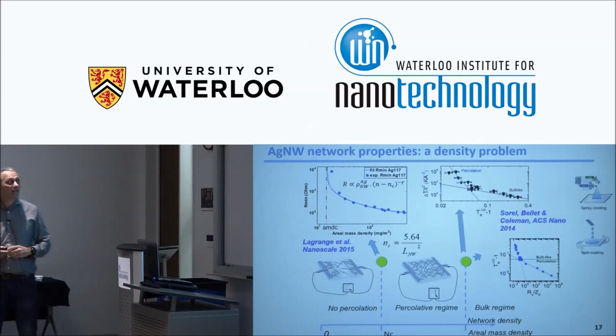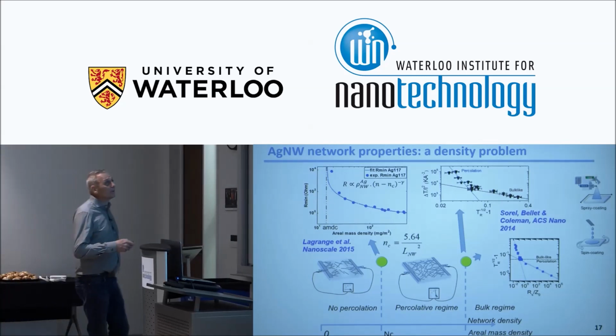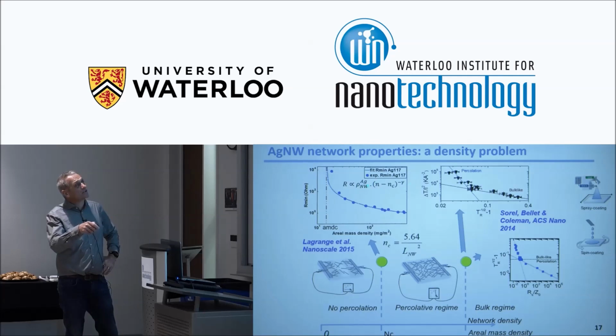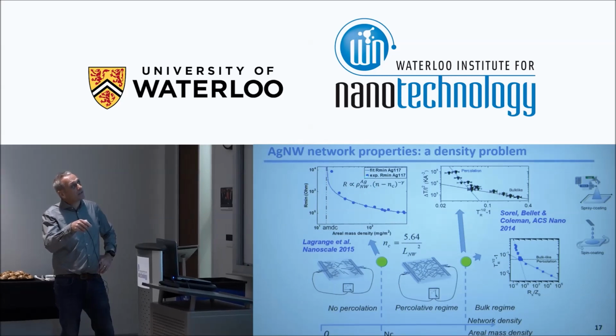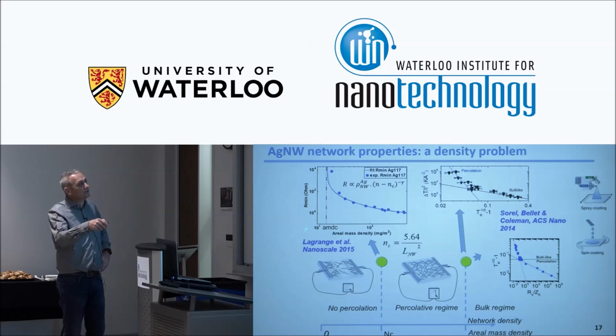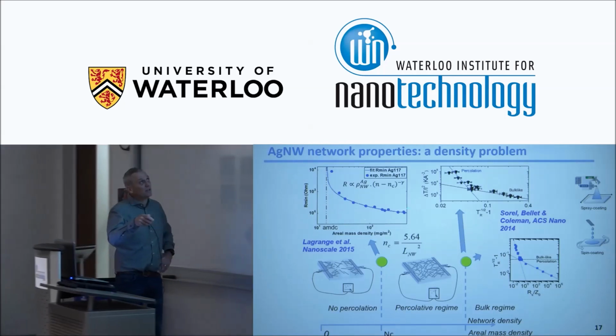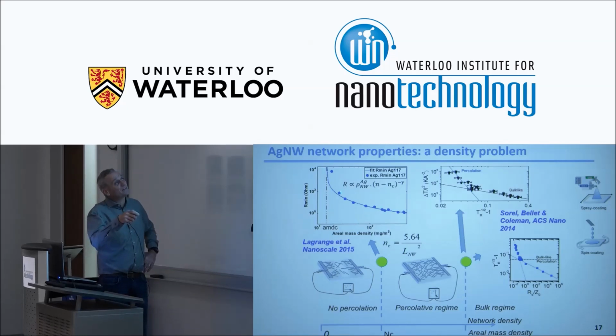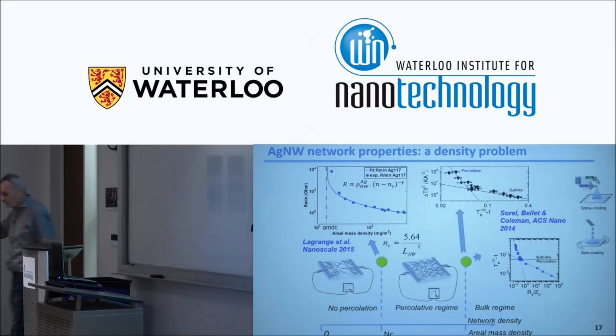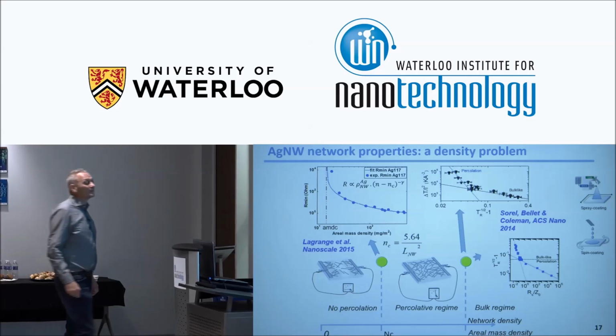It has been studied for more than 4 decades by people. And especially this is the percolation theory, saying that n, the density, the number of nanowires per unit area, minus this critical density, to the power minus gamma, is proportional to the resistivity. That means the resistance is proportional to the resistivity of silver nanowires, which can depend on the diameter, times n minus nc to the power minus gamma. And I'll show you later on that experimentally, if we plot, for example, the minimum of the resistance observed during a thermal ramp versus the areal mass density of the network, we have these points, and we can fit them easily with this curve, and it's working pretty well. And here we have the critical network density or critical areal mass density, and when you are reaching this value from just above, the resistance is diverging.